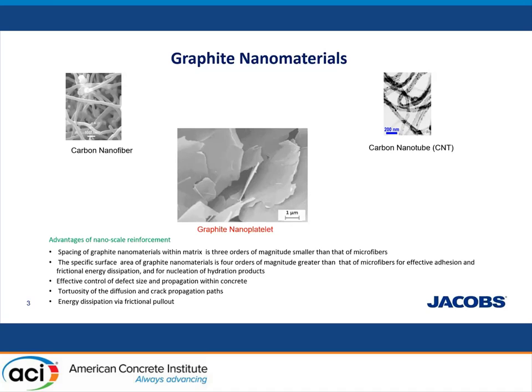Fundamental studies in this field have demonstrated the value of different graphite nanomaterials, like carbon nanotube, carbon nanofiber, and graphite nanoplatelet in cementitious paste. The graphite nanomaterial considered in this study is GNP — graphite nanoplatelets. These relatively low-cost graphite nanomaterials, which are produced at industrial scale right now, offer distinct geometric and performance advantages rooted in their nano-scale dimensions and substantially reduced structural imperfections when compared with conventional carbon fiber, which comprises an imperfect arrangement of graphite sheets. Graphite nanomaterials offer distinctly high mechanical and physical attributes as well as enormous surface area when compared with microscale traditional fiber.